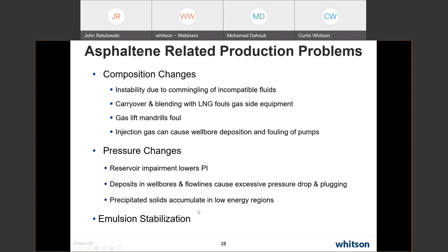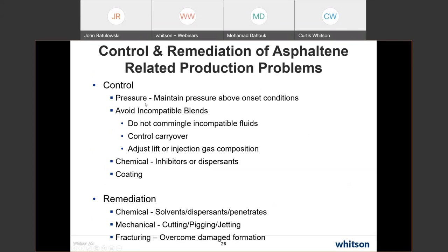To control this, for pressure, you can try to maintain pressure above onset conditions, but that's rarely possible if you want to actually produce the field. Avoid incompatible blends, so you don't want to dump a condensate into an asphaltic oil in a separator. It will cause problems. Control carryover. We've had carryover of asphaltic liquid phases that get into the gas system. And as soon as they hit all the LNGs and everything that are flying around the gas system, it causes a lot of problems in pumps and compressors and other things.